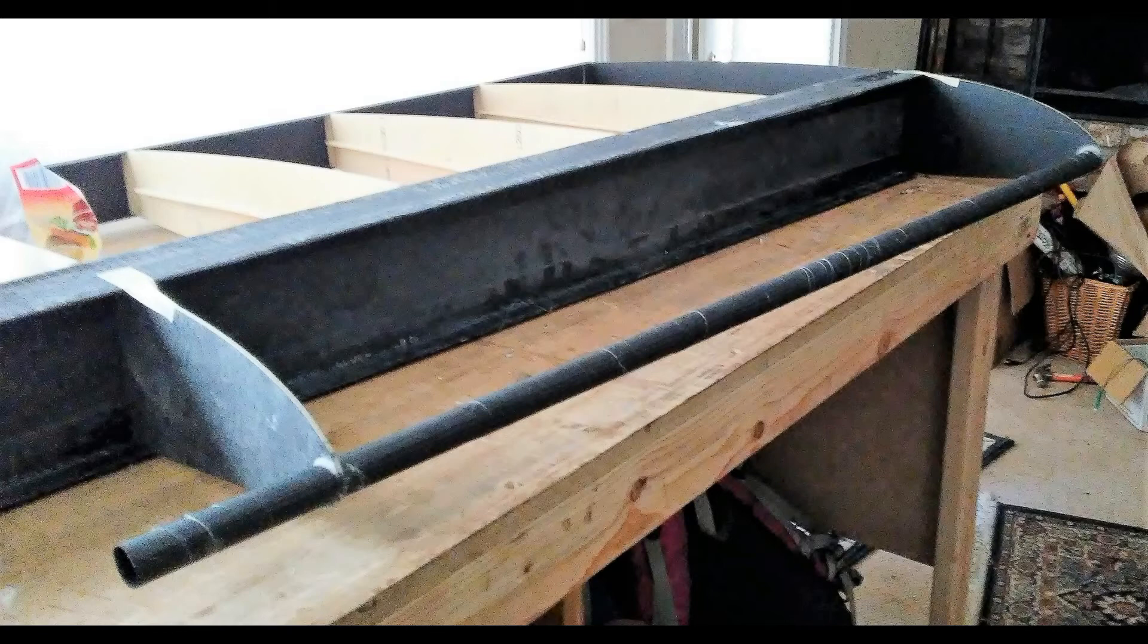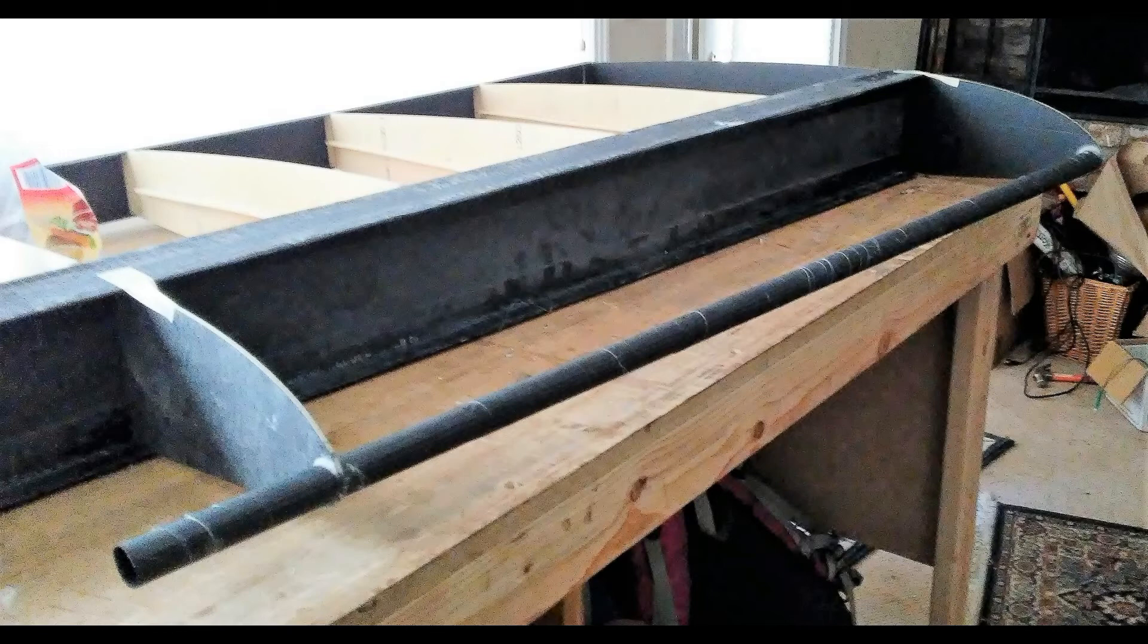At this point in the assembly, I have taped the nose ribs in place and bonded the leading edge tube to the nose ribs. The nose ribs are made from the same materials as the aft ribs at the root and tip. At the root end of the leading edge tube, I installed a short section of aluminum tubing that serves to align the wing to the root structure and transfer the torsion loads. This aluminum tube is filled with a wood dowel to prevent crushing of the tube and is then bonded and riveted into the carbon fiber tube. To avoid galvanic corrosion of the tube, it is necessary to use stainless steel rivets and have a layer of fiberglass on the inside of the carbon fiber tube to prevent direct contact between the carbon fiber and the aluminum.